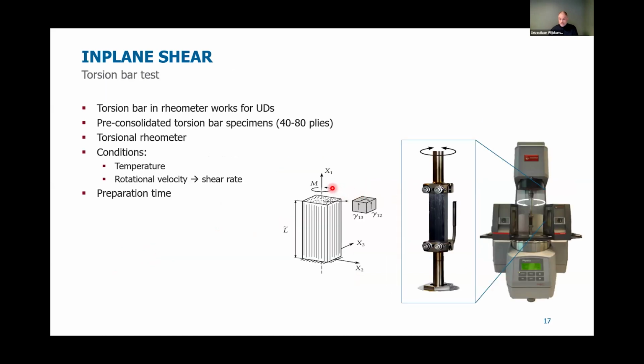So we chose then to look at in-plane shear through torsion of a thick beam. So we create thick laminates, 10 millimeters thick or more. We cut bars, put them in the rotational rheometer, and can control very well the temperature and the angular velocity in the rheometer. And with some analysis, you can get in-plane shear behavior from that specific setup. Big drawback of this test is the preparation time and the amount of material that you need.